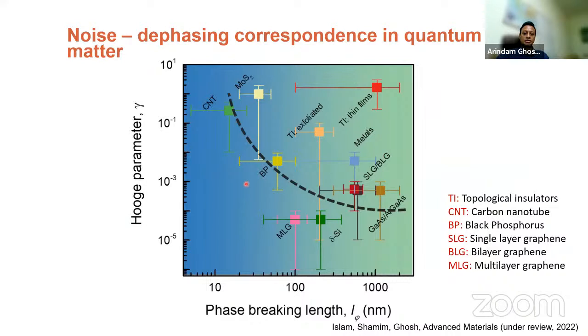There is a large number of different materials, and you can see if the Hooge parameter, the noise parameter, is large, then usually the phase breaking length is short. That means the quantum coherence in the system is usually short, and it reflects the dephasing by structural defects, by various kinds of two-level systems in these materials. So if you want long phase breaking lengths, which are required for quantum applications because the electron retains its phase memory, then the Hooge parameter must go down significantly. So this is quite exciting for the overall understanding of quantum materials.